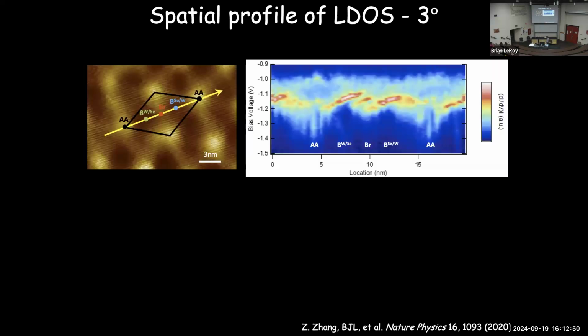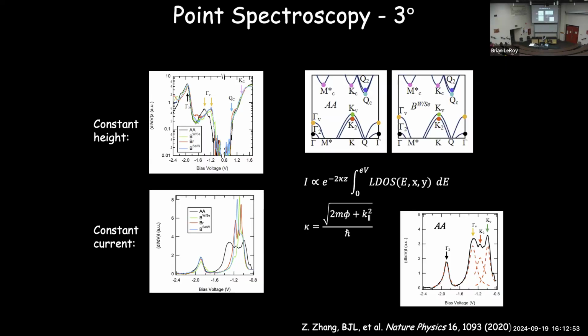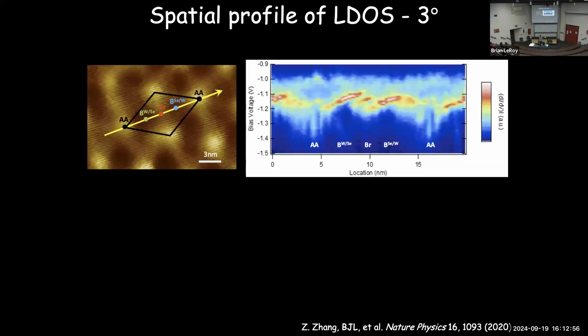So now, instead of looking at the density of states at a single point, let's map the density of states as a function of position across the sample. I'm only going to show you the valence band because that's where the interesting physics is occurring. The color scale is the density of states. Dark colors, blue and black, are zero density of states. White is high density of states. This is the band gap up here. This is the band edge here. And you can see there are states that show up near the band edge at different positions along the sample in space. There are some here, here, nothing really happening at the AA site, et cetera. So that's a one-dimensional cut through there.